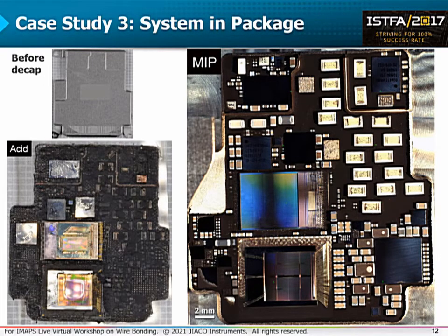The module we have here has a size of around 2.5 by 3 centimeters, and as can be seen on the left, the module decapsulated by acid has been severely damaged by corrosion, and wire bonded stack dies also suffered from corrosion. Moreover, multiple flip chip CSPs and passive components were simply removed from the substrate by acid etching and left behind only some soldering marks. On the image on the right, halogen-free MIP has been applied to open the entire module, and MIP decapsulation was run fully automatically until the wire bonded stack dies, flip chip CSPs, and passive components were all cleanly exposed without damage.